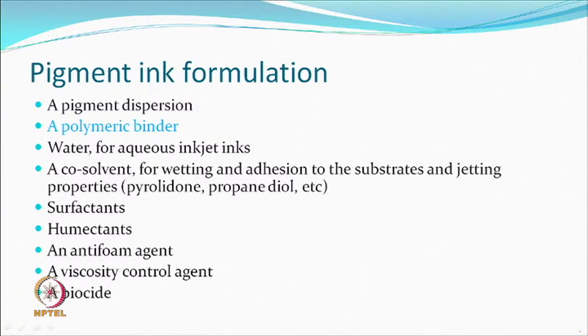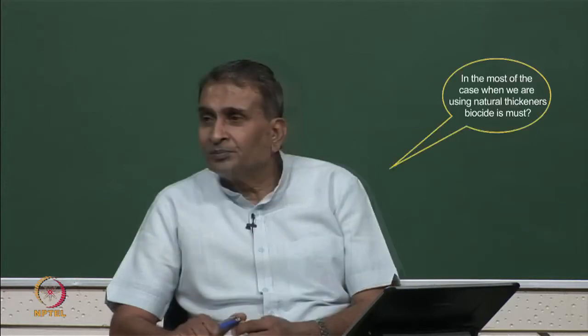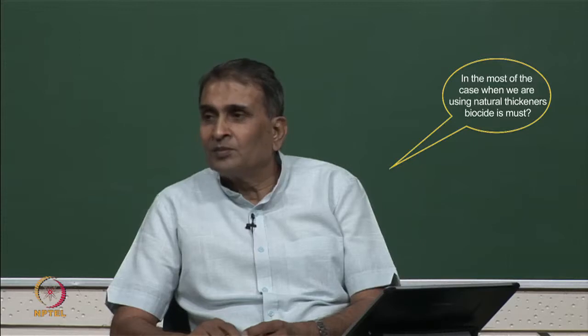A biocide may be needed because you may want to store the ink for months together, and any aerobic or anaerobic microbial growth must be prevented. While biocides are also required for normal printing processes, in conventional printing you would finish a paste within a week. Here you may be looking at six months to one year of storage, so the requirements are very different. In cases where natural thickeners are used, biocide is a must. A biocide such as a copper compound or a cationic agent may be used, with durability requirements being much larger than for conventional printing pastes.